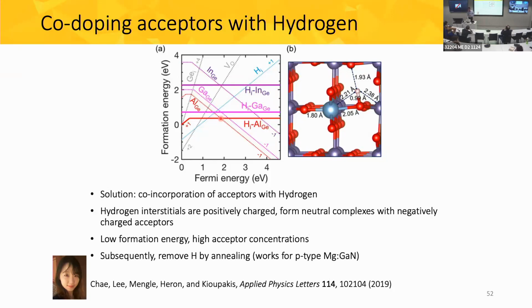Yeah, so a sign for a complex is when you have a positively charged defect and a negatively charged one, so that the Coulomb attraction will bring them together to form a neutral object. But once it's neutral, that's when I think the entropy wins, and then you get a random dispersion throughout your sample.